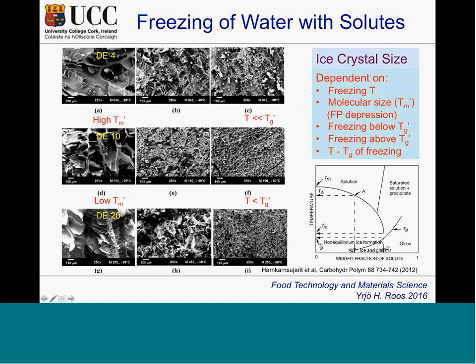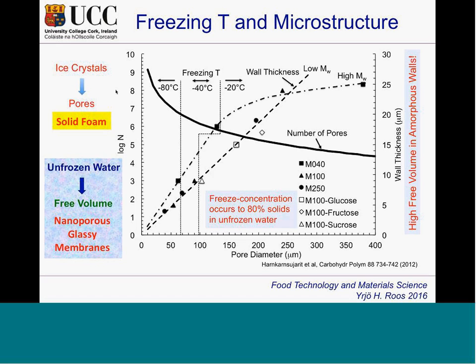This is an example of different DE values of maltodextrins. We can see that DE20 makes a very different structure from DE4. They are frozen at minus 20 or minus 40 or minus 80. So the freezing rate has an impact on the size of the crystal, but so does the DE, which relates to the melting point depression. Based on that, we could actually make an analysis of the number of pores, which means how many nuclei, how the nucleation happens, and also what the wall thickness is, which is important for protection of sensitive components inside the freeze-dried matrices.